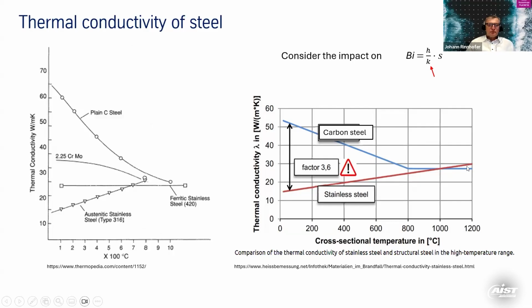And then they go up to the final heating temperature at 1200 degrees, and it is very much the same. So there's a huge difference in the Biot number when you look at the area below 800 degrees. So this stainless steel is already a thick material, so it has significant temperature differences in the stock in comparison with a carbon steel, for example, in certain heating conditions. So you cannot say steel is equal to steel. You really have to look at the type of steel and at the heat conductivity when you look at the heating process. So that can be a completely different heating strategy for stainless steel in that lower temperature area, up until 800 degrees.